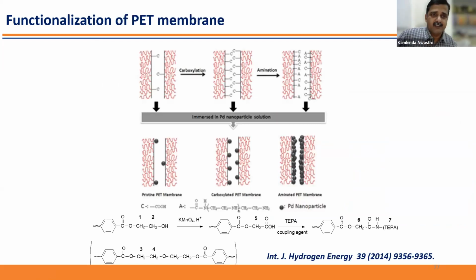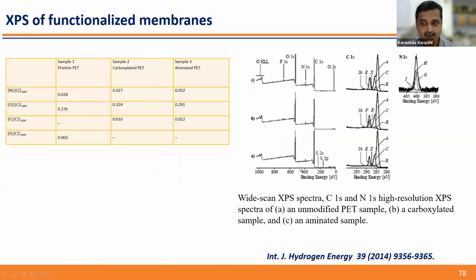So we tried with our track-etched membrane, where we were unable to control the selectivity. So this is a process called carboxylation and then amination. Carboxylation means having this COOH group and this amine NH2 group, and then we further deposited this palladium. So in pristine PET membrane, there are few carboxylic groups, so attachment is very limited. But when we further carboxylated, there is more attachment of this palladium nanoparticle, and in amine, you can see a lot, because it has more ability to attract these palladium nanoparticles.